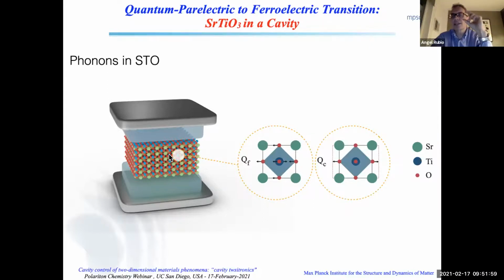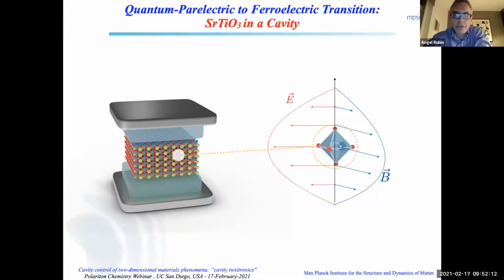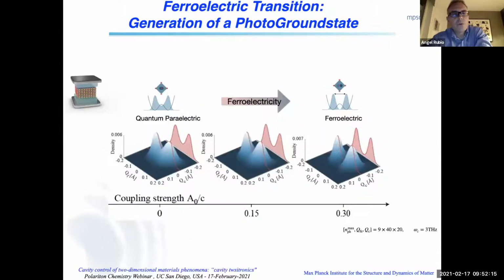And here there are two modes that are extremely important. It's the titanium and oxygen separation, plus the fact that when you move the two atoms, the lattice elongates and goes to the tetragonal phase. If those are the fields, then let me give you what you get, because this was more for the summary of the talk. If there is no coupling, you get what you expected: the material is a quantum paraelectric, which is dictated by this double well potential, in which the system wants to have polarization in this direction or polarization in the opposite, but on average you get zero. This is the quantum solution of the problem, which gives you a zero polarization of the system with two lobes.